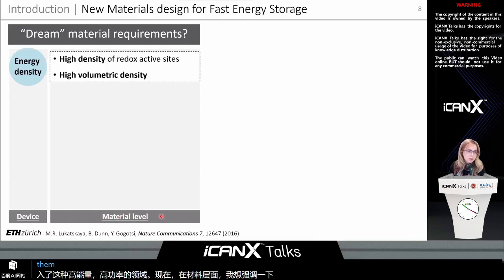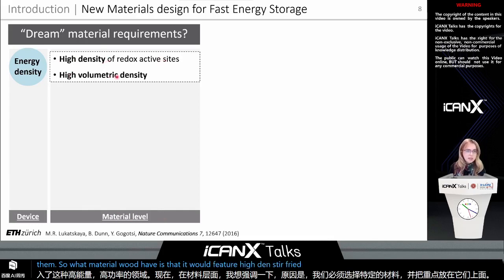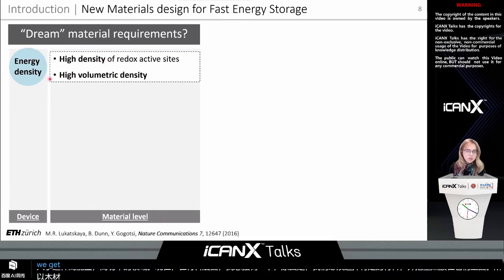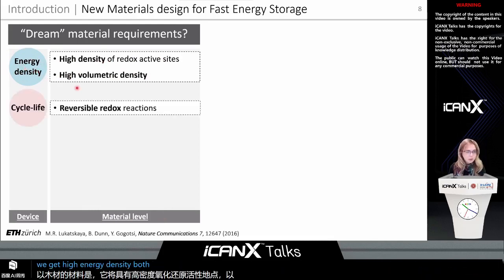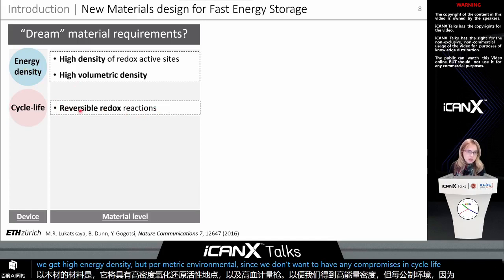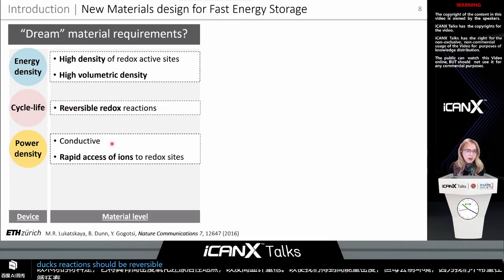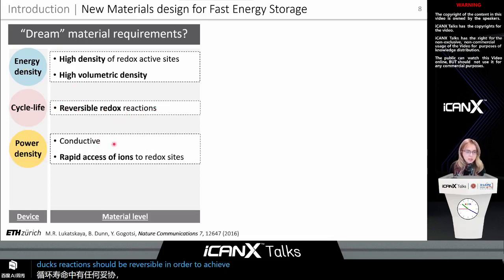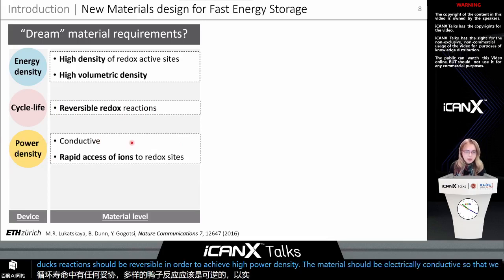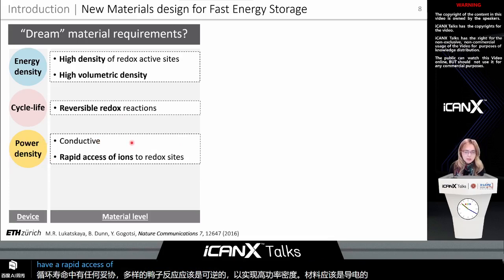So the dream material would feature a high density of redox-active sites, as well as high volumetric density, so that we get high energy density, both gravimetric and volumetric. Since we don't want any compromises in cycle life, the redox reactions should be reversible. In order to achieve high power density, the material should be electrically conductive so that we have rapid access of ions to the redox-active sites.